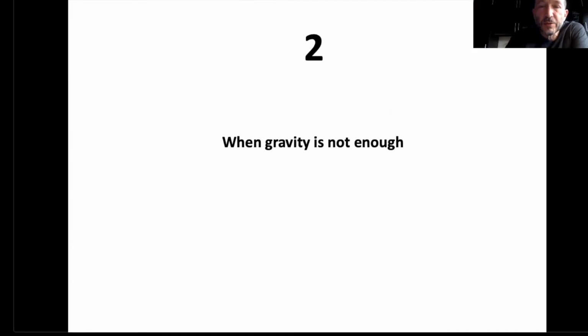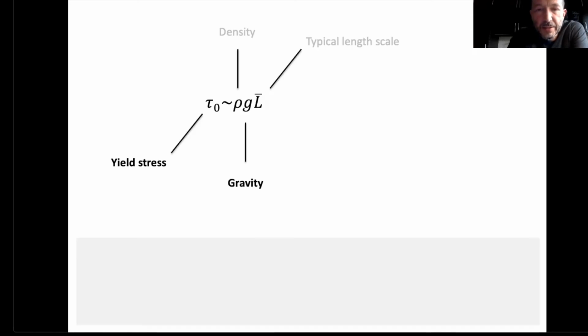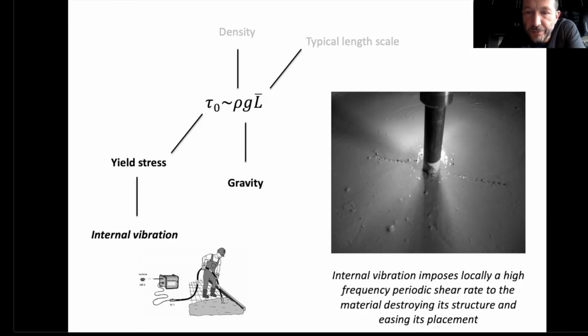Let's move now to our second part, when gravity is not enough. So in this case, I'm going back here. Density cannot be changed. If you have difficulty casting a given cement-based material, you won't change the density because of that. The typical length scale is imposed by the object you want to produce. And you can play on two things, yield stress or gravity. You could decrease yield stress by using admixtures, which is out of the scope of this lecture today. But if you don't want to change the mix design, you can change yield stress by using internal vibration.